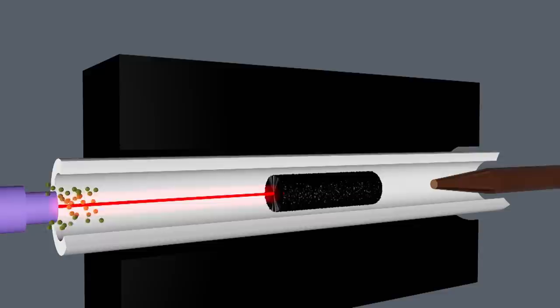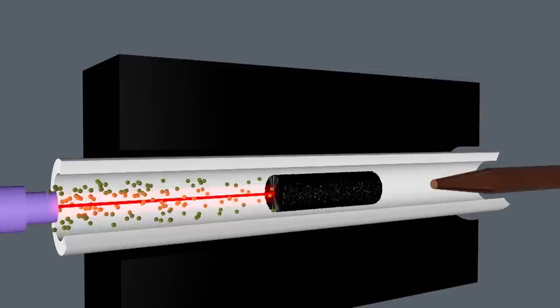The researchers thereby discovered a much less toxic manufacturing process. Using gas and a laser, the smallest carbon strands at the top of a charcoal stick were dissolved at 1,200 degrees. They then accumulated on a cooled collector. These new carbon nanotubes were easier to separate from toxic residues. In 2011, the team patented their process.